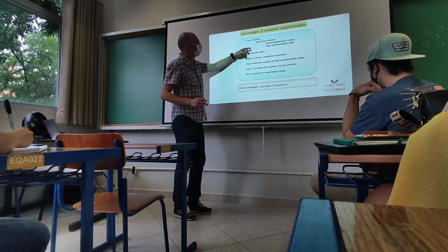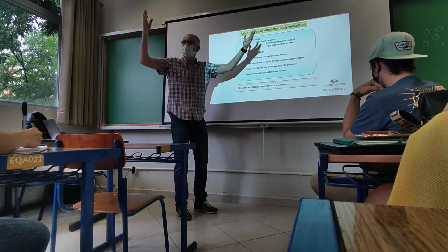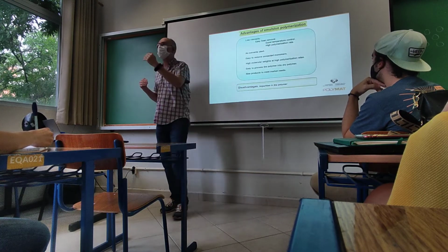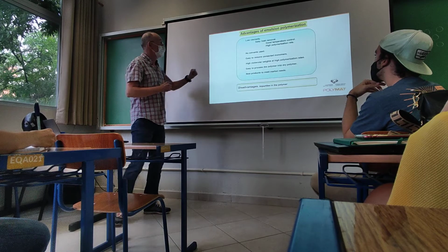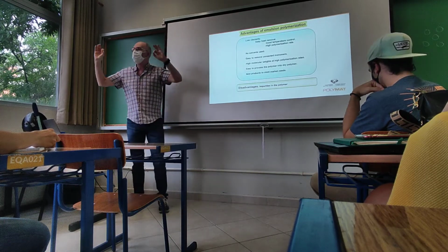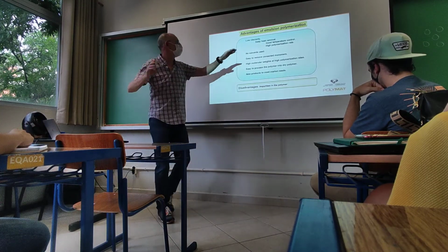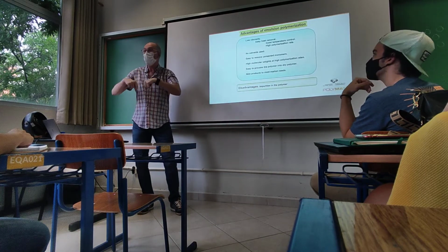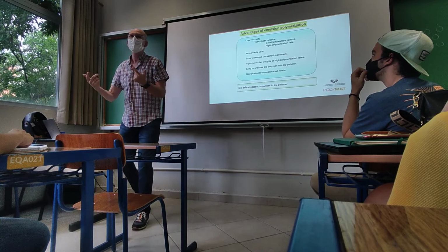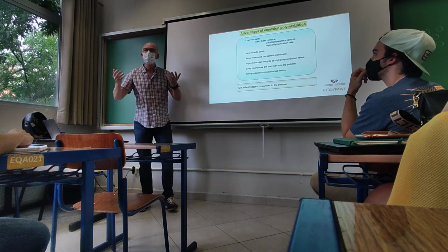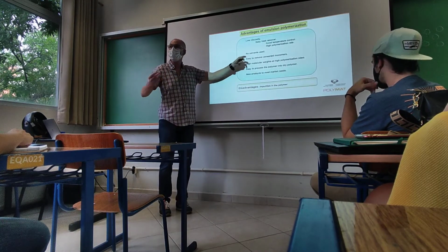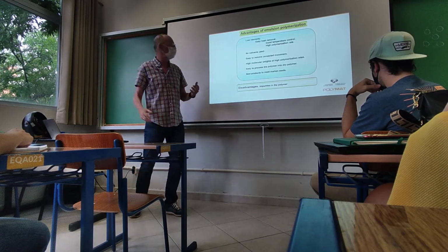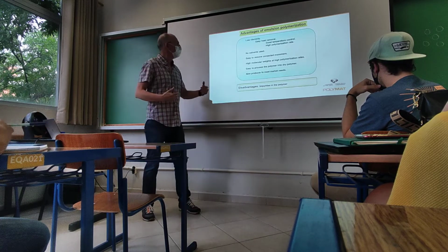Low viscosity, therefore easy heat removal in large reactors, good temperature control, possibility to have high polymerization rates. Okay? It's a green technology. Already in the 40s, this was a green technology. No one claimed that it was green at that time. But nowadays, we are concerned about the environment. Emulsion polymerization uses water as solvent. Okay? So from this point of view, it's a green technology, environmentally friendly.